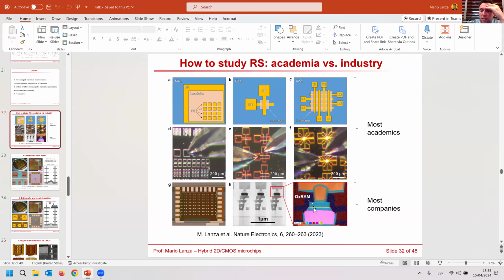The only difference in our case is that we transfer boron nitride, and boron nitride is grown on a different substrate. It is transferred at the wafer scale with the process being used by IMEC, for example. And then the bottom electrode, you can put the bottom electrode that you want. And at the top electrode, you can put the top electrode that you want. So it is completely compatible. The boron nitride can be grown at the wafer scale with the machines that I have shown. It's a CMOS compatible temperature transfer process. So there is nothing that prevents you from doing it.